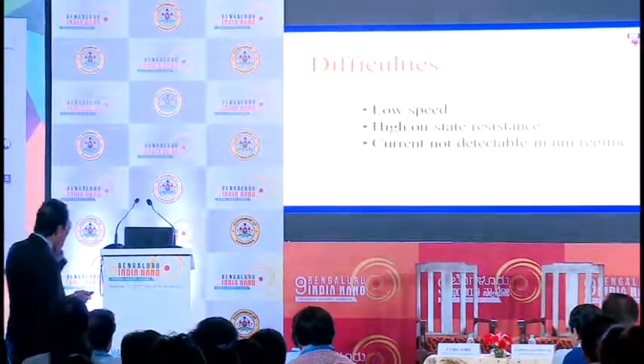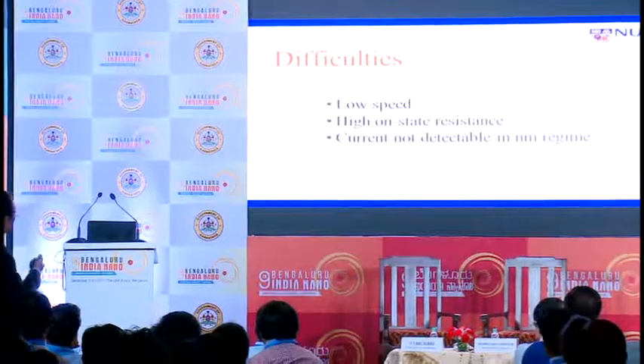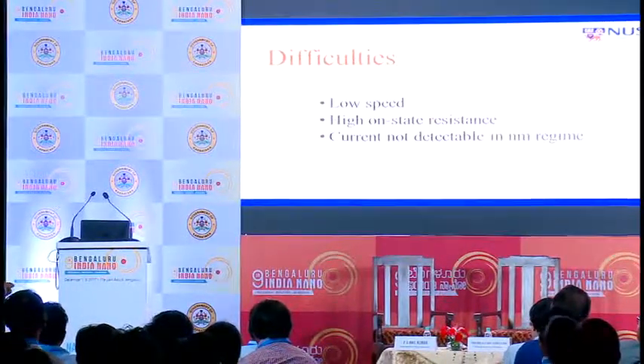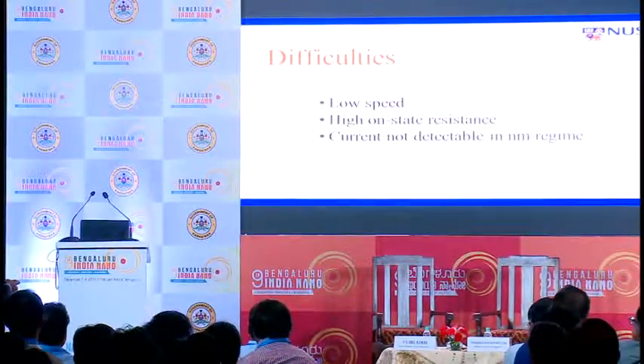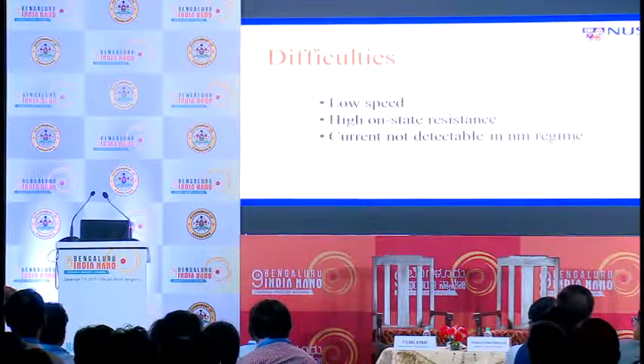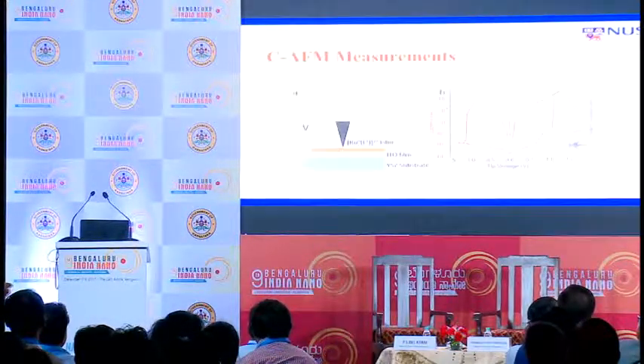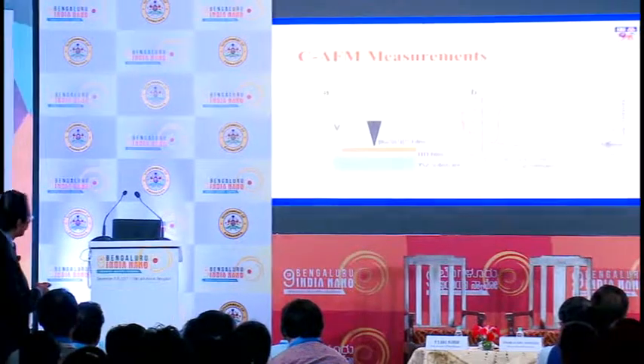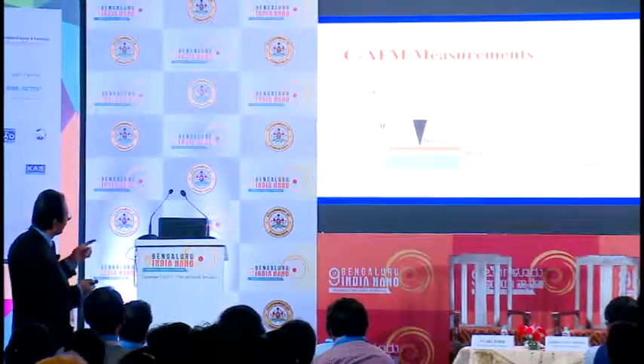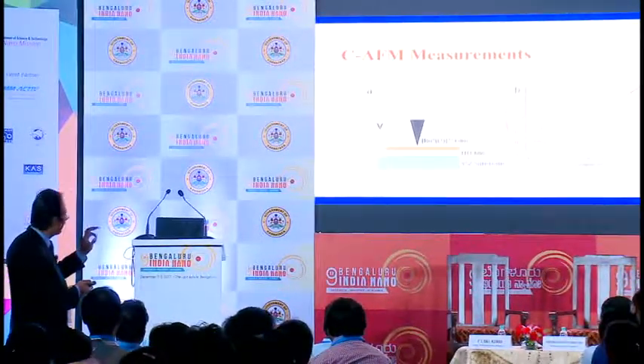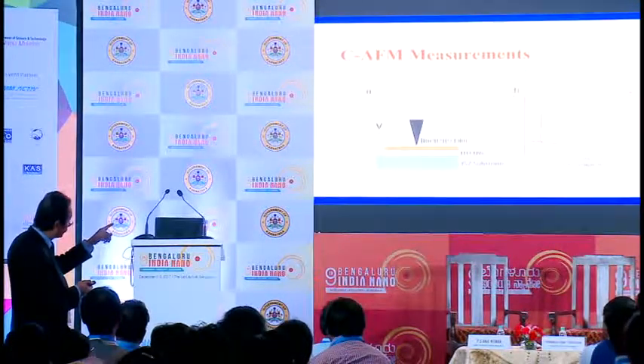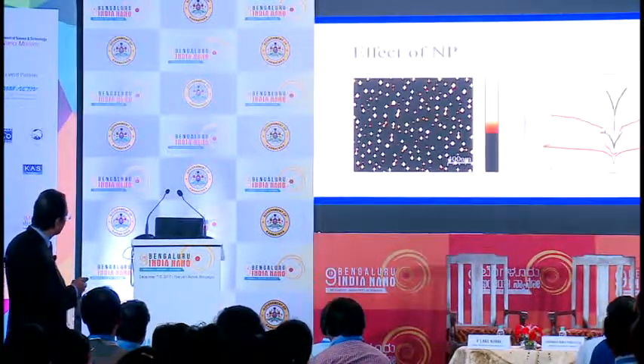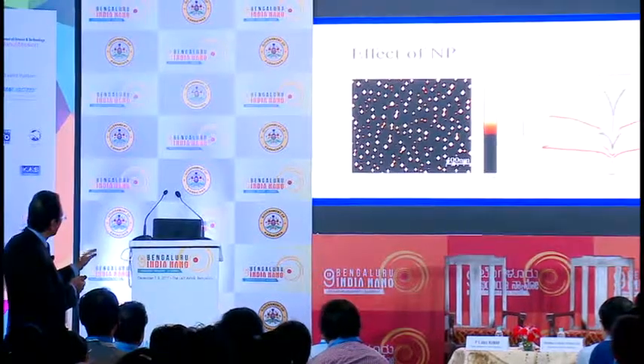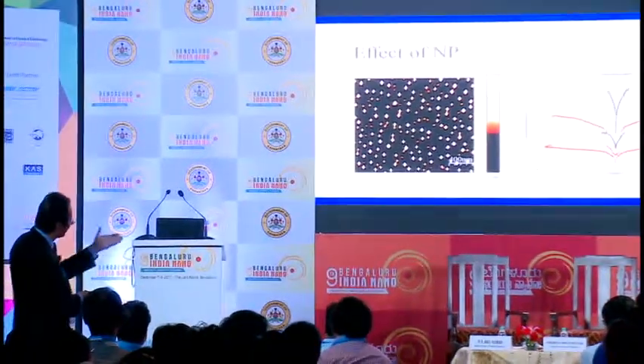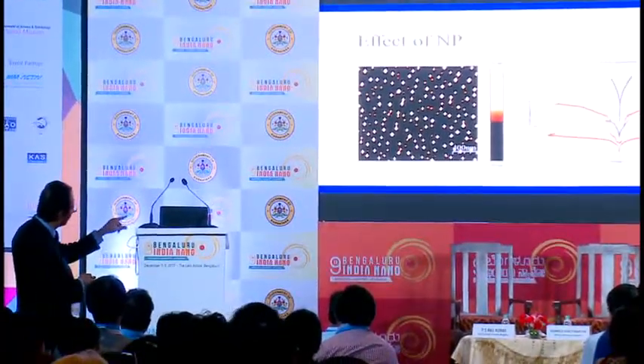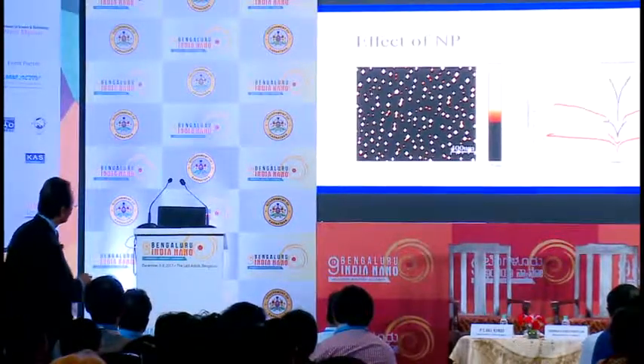When we tried to first publish it in Nature, the referee pointed out a number of things. Look, your device is only microsecond, and you have large on-state resistance, and the current that you're generating is not easily detectable when you make a nano device. So what Steve first noticed was that when he used conducting AFM tip, he could get the device to switch at very low voltages. So what he did is he put some gold nanoparticles on the bottom electrode, and the device now switches on. You see the black curve at half a volt, which is remarkable.